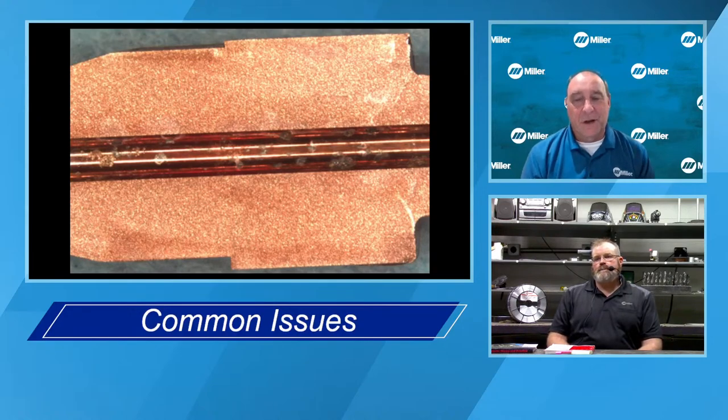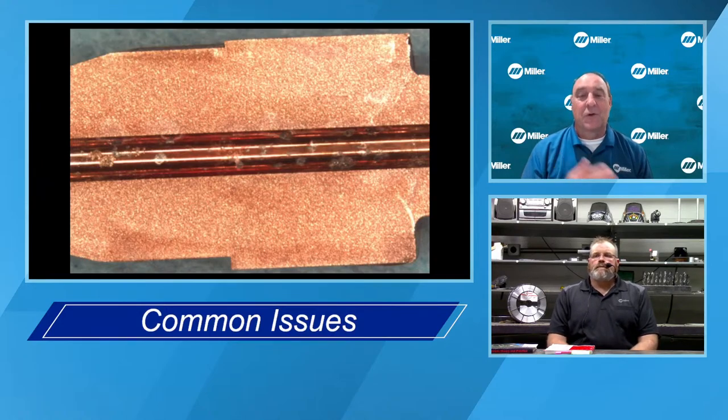Right. Another thing regarding the contact tips Cody mentioned is that typically an aluminum contact tip is a little more oversized than a steel contact tip. So for example, if you're using 035 aluminum wire, don't use an 035 steel tip. You want to use an 035 aluminum tip, which is probably going to be around 039. Again, for aluminum 4043, 047, you want to use the right contact tip. You don't want to use an 045 steel tip for that, because you need a little bit more room in there for the aluminum transfer.